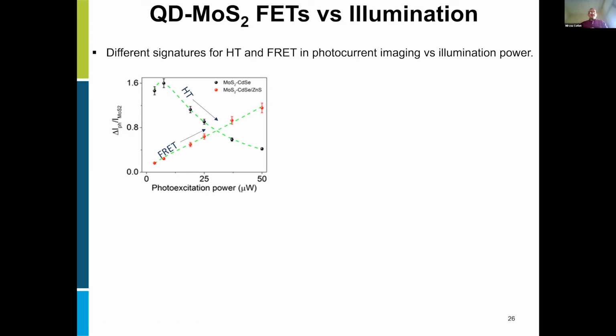But the most interesting part coming out of this study is that when you start to increase the amount of light impinging on these transistors, you see different behaviors for the two types of architectures. For the one functioning on core shell quantum dots, which performs energy transfer with the 2D material, we see that increasing the photoexcitation power, we create more and more photocurrent, while for the one functioning on core only quantum dots, there is some increase in the beginning, and then the produced photocurrent is inhibited.